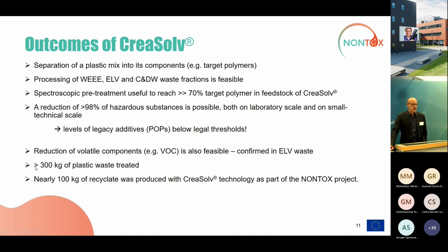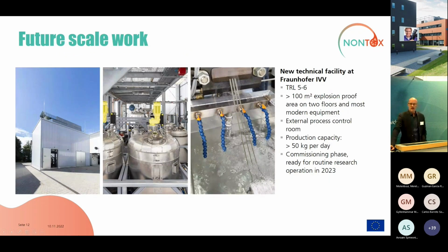In the end, we treated more than 300 kilos of plastic waste in our trials, which is with the small technical line really much of effort, and we could produce and deliver nearly 100 kilograms of recycled materials to our partners. This was quite an effort, and we are quite proud of doing this, but it's of course not good enough for the industry. And this is why we have now the pleasure to announce that there will be a future larger scale of work.